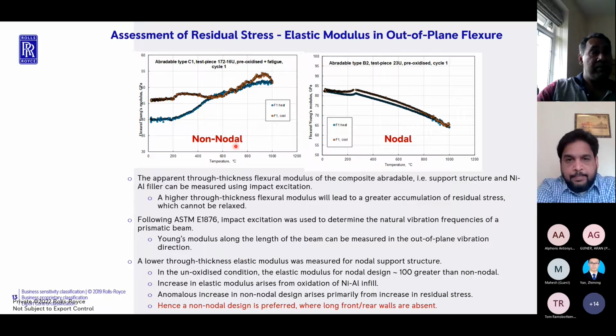These are examples of the graphs that we got. If you look at the nodal design, you see a typical case where the elastic modulus decreases. When I say elastic modulus, it is the effective elastic modulus, not the elastic modulus per se of a metallic system, because this is really a composite between a metal and the oxides that are packed in between the interstices.